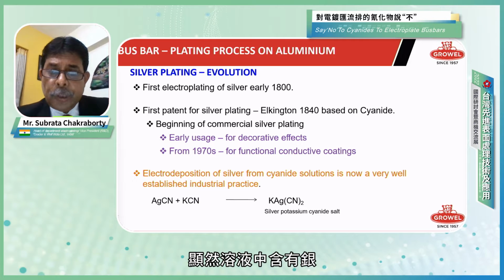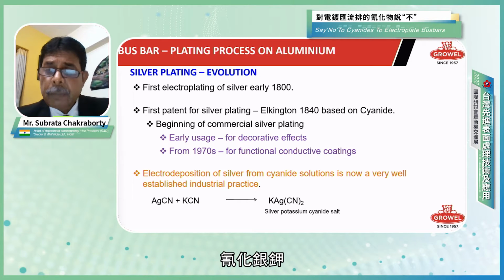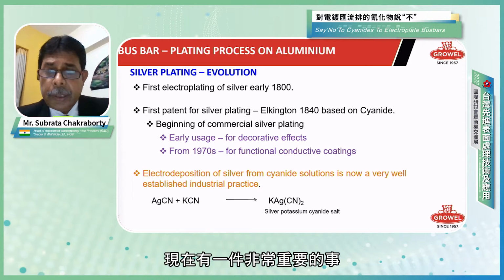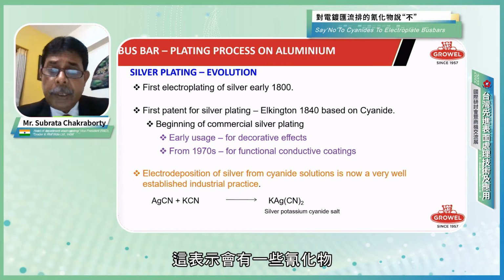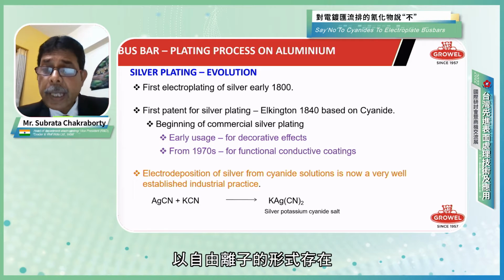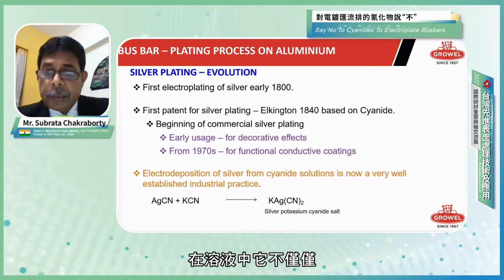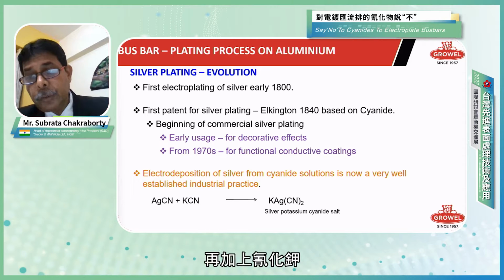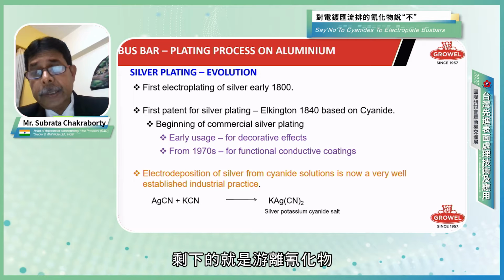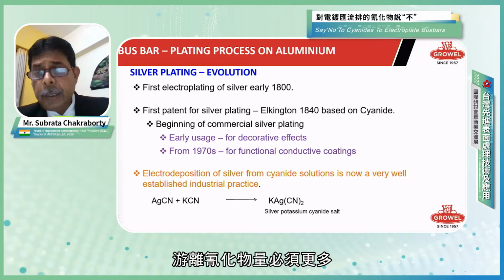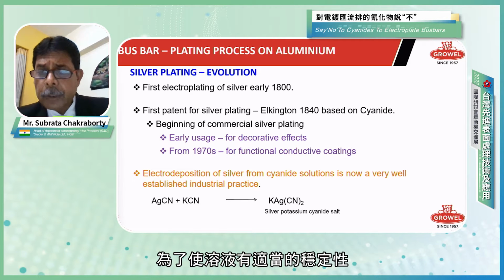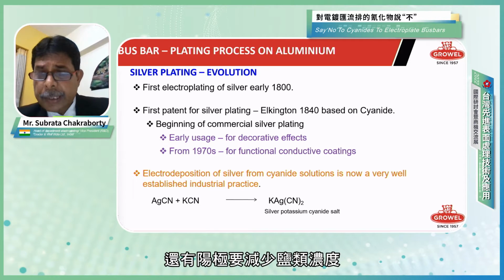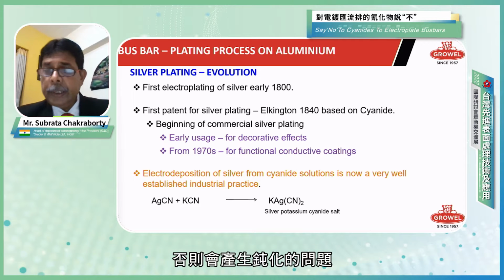Obviously, in the solution, it contains potassium silver cyanide. A very important thing here is that we need to have free cyanide, meaning some cyanides remain as free ions, because in the solution it doesn't remain only as silver potassium cyanide plus potassium cyanide. Whatever remains is the free cyanide. The free cyanide level has to be higher, let's say 120 grams per liter, to have proper stability of the solution and less anode polarization. Otherwise, it creates a passivation problem.